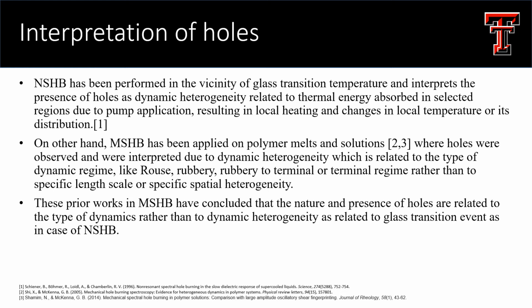In case of non-resonant spectral hole burning, the experiments were performed in the vicinity of glass transition temperature and interpret the presence of holes as dynamic heterogeneity related to thermal energy absorbed in selected regions due to pump application, resulting in local heating and changes in local temperature or its distribution.